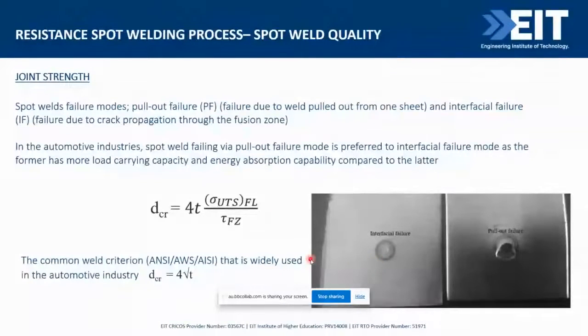For example, the welding standards like AWS, American Welding Society, and so on. They have created the weld diameter that's required in order to achieve a pull-out failure: D should be equal to 4 square root of T. Okay. Now, this is a common welding criterion that we are using in the automotive industry. There are some variations to this also. JIS, Japanese Industrial Standards, use D equals 5 square root of T, right? So this is 5 square root of T rather than 4 square root of T. There are some slight differences in this variation, right?